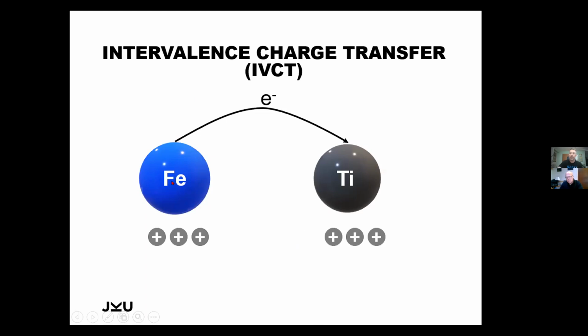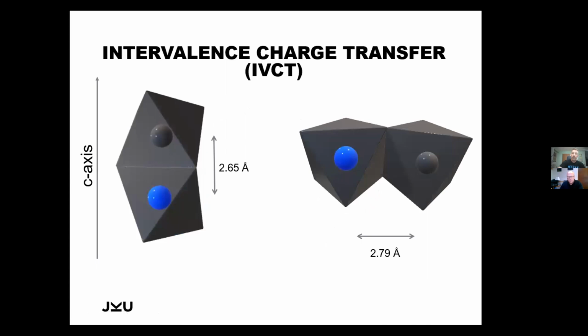And of course, one prerequisite is that the iron must be neighboring the titanium. We cannot shoot the electron across large distances, so they must be proximate to each other. And again, this is a mechanism where an electron changes its energy level, therefore we see some absorption. Here we have two different cases. We might have two of these oxygen octahedrons which are connected via one face. So 1, 2, 3 triangles are shared by these two octahedrons. And then we have here the iron, here the titanium, and the distance between these two ions is 2.65 angstroms.